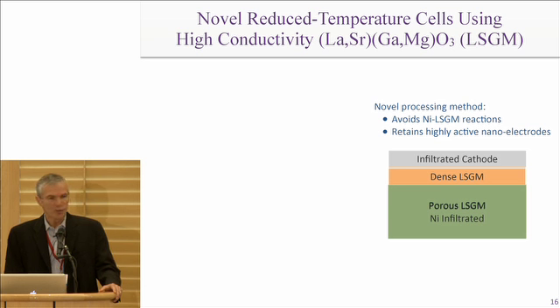As I mentioned, one of the key problems with making a lower temperature cell is to get away from yttrium-stabilized zirconia electrolyte. So we've been looking at this newer electrolyte material. It's a lanthanum gallate, or LSGM for short, which has a higher conductivity at low temperatures. But one of the problems with this material is that it's traditionally had processing problems, and one of the common electrode materials contains nickel, for example. Well, that reacts strongly with LSGM. So that's a problem. Another one is, to get these things to work at low temperatures, you really need highly active nano-electrode particles.